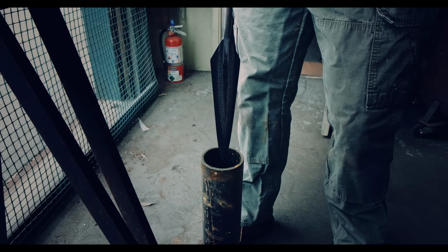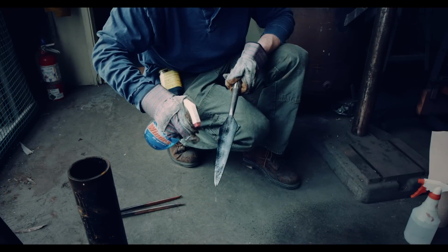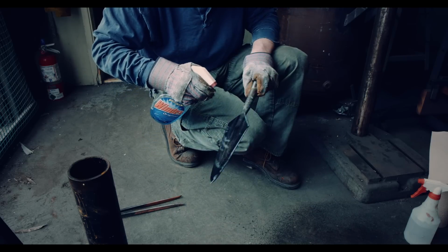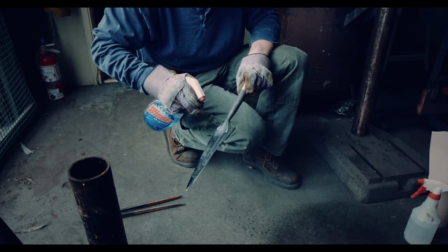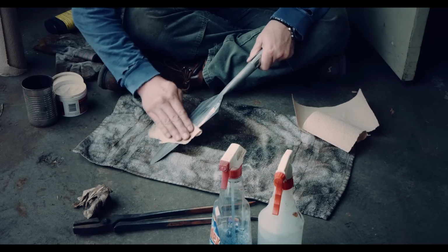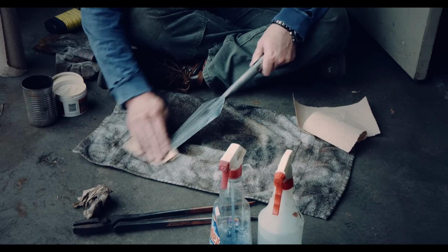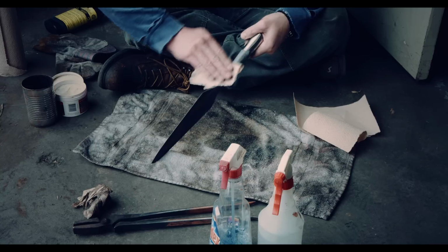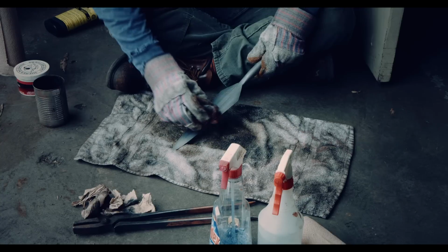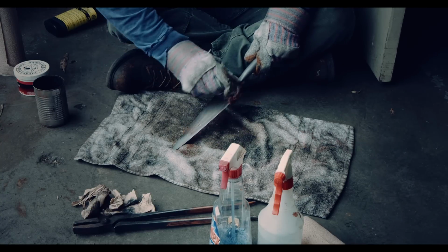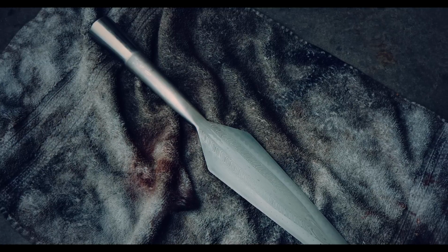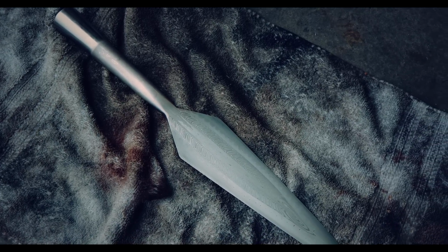What follows is my usual routine after etching. It involves some metal polish and some iron oxides. This is what works mostly fine for me, but that very much depends on the materials. For this spear I was using wrought iron from a different source, and it does not stand out as much against the high carbon steel as I would have liked. Alright, here's the polished pattern.